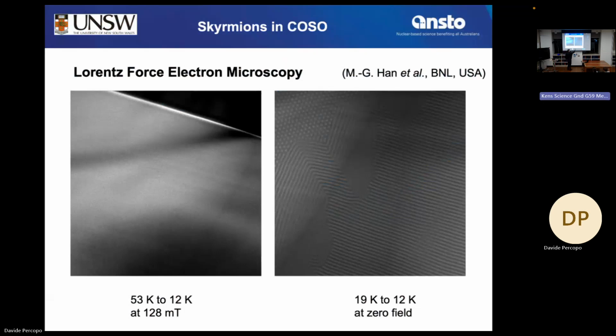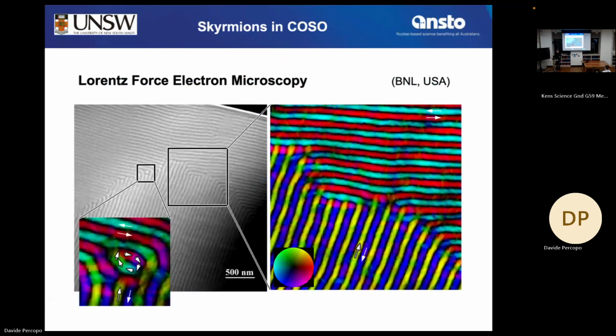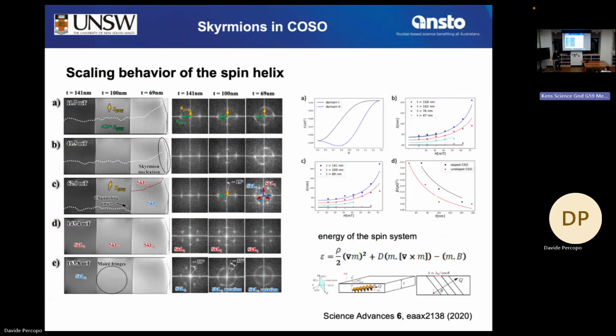If you look closer, we have two domains, that one and that one, 90 degrees from each other. And in the upper corner, you see the starting point of skyrmions, quantum dot points, hexagonally arranged. Interesting, sometimes just right in the middle, you see a single skyrmion popping out here in that corner. And then it disappears again. So that entire structure is quite wobbly. I'll skip that. So we did detailed analysis of that.